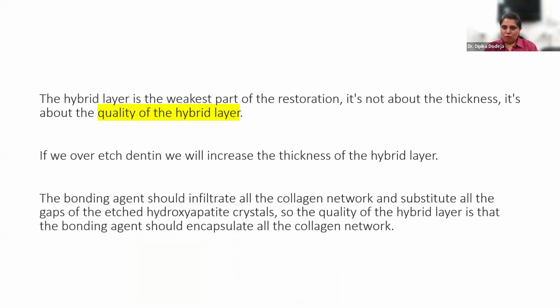If you have over etched, the demineralization is quite deeper, but the bonding agent may or may not penetrate to the entire thickness. So this gap which is created between the residual demineralized dentine and the penetrated bonding layer is what will act as a weak link. So it is not about the thickness of the hybrid layer, it is mainly about the quality of the hybrid layer. The hybrid layer should be formed when the entire collagen is enclosed in the resin.